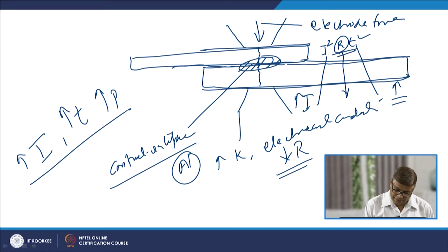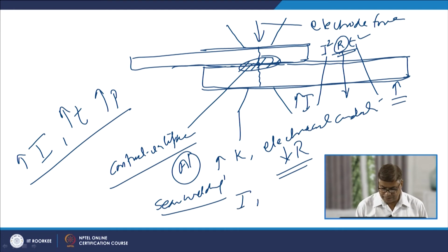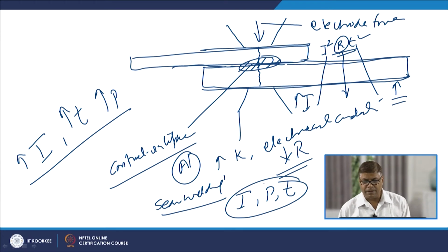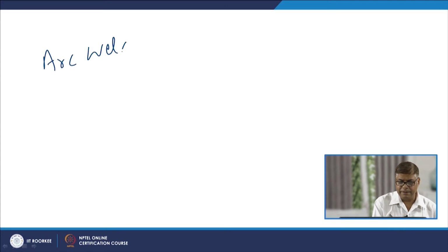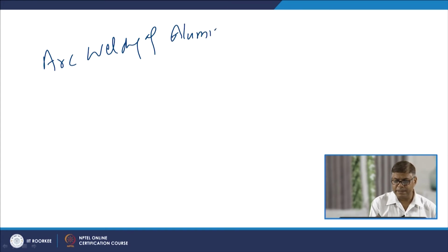Likewise, in the case of seam welding of the aluminized steels, the current, the pressure and the time for which current is allowed to flow are all increased, so that the required amount of heat can be generated in order to produce the sufficient nugget size as well as thermal softening of the metal. Coming to the arc welding of the aluminized steels.